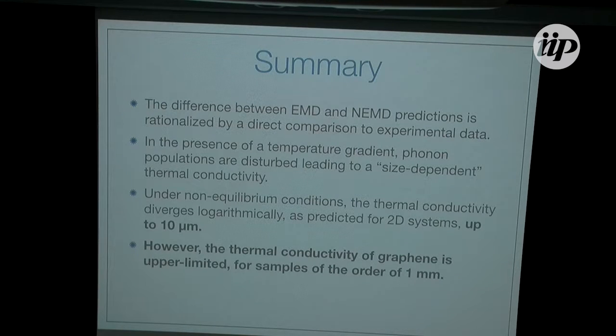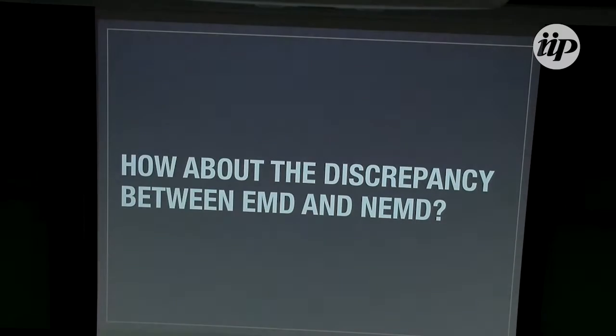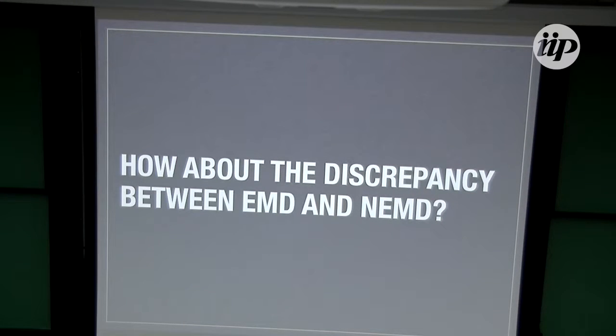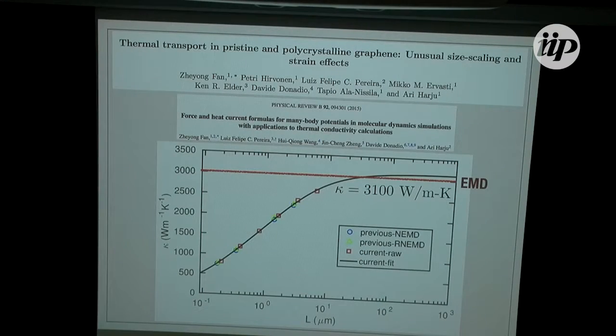So the thermal conductivity diverges logarithmically up to 10 micrometers, but it does converge for graphene patches of about 1 millimeter. But still, equilibrium MD is just wrong. You just throw it away. You can't calculate thermal conductivity with it anymore. Well, I was almost ready to accept that fact. And then